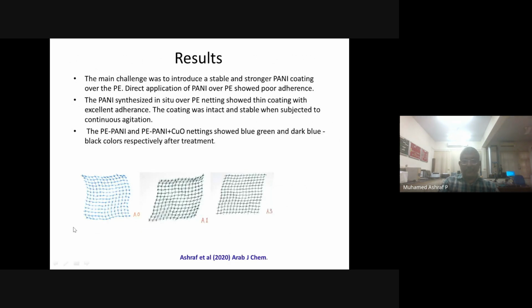This is pure polyethylene. This is the polyaniline, the bluish green color. And the third one is where the surface has become polar, because now it is ready. You will not find that a polyethylene containing polyaniline changes much. By color you can say that polyaniline is added, but by seeing it there are not many changes in the net. The aquaculture cage net is just as flexible as earlier.